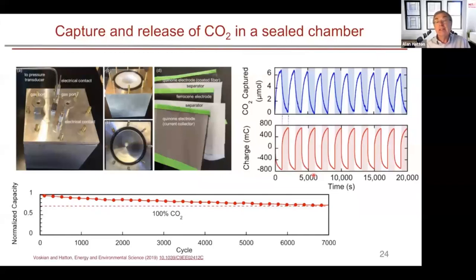The overall capacity was pretty high. This is the normalized capacity over about 7,000 cycles. There was some reduction in capacity, which we understand why that is, and we know how to improve on that. But the important part is that we got greater than 90% Faradaic efficiency, and as I'll point out a little bit later, we got about 40 to 50 kilojoules per mole, which is a very respectable energetic penalty to pay for this overall capture and release cycle.